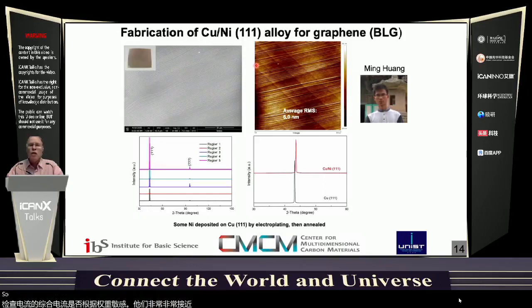So after the electroplating on both sides, we heat treat, we anneal for about 10 hours, again, close to the melting temperature of copper, and we end up with single crystal, but now with nickel present. So why are we doing this?